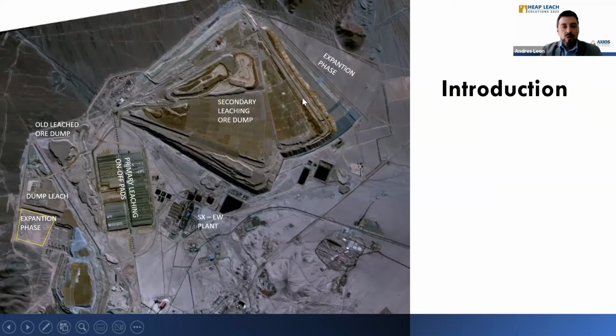Taking that into account, the operation was looking for different alternatives among the materials they had available. For that reason, previous studies determined to reuse the same leached ore from this secondary leaching. In summary, the operation started to look among the same materials there. So they looked at these old leach ore dumps as an alternative to use this material as overliner, with as little processing as possible.